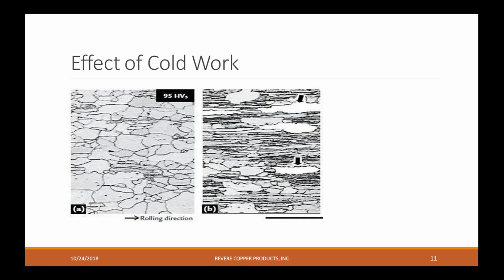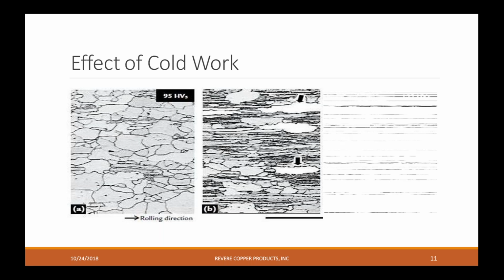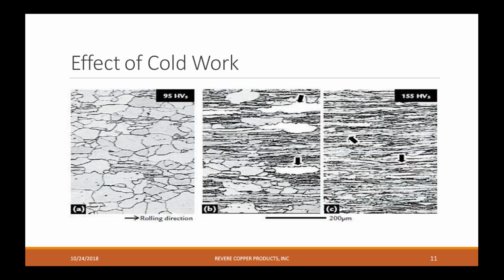Then as you start to do a reduction through rolling, those grains get squished. They start to get elongated and directional. And eventually, they almost get smeared out. You can barely see the grains in the last picture. And that's after quite a bit of cold rolling, it would look like that.